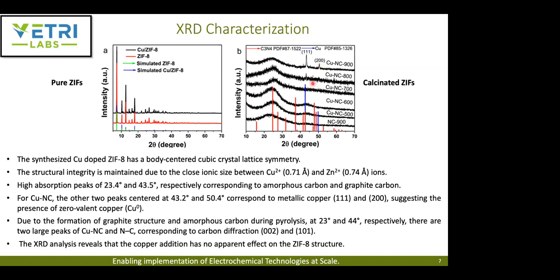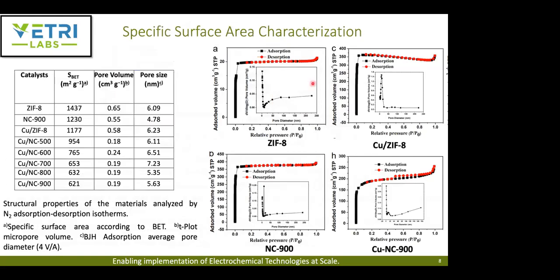And one thing maybe they kind of missed is the XRD analysis. They said the copper addition has no apparent effect on the ZIF-8 structure. And then they did the specific surface area characterization.